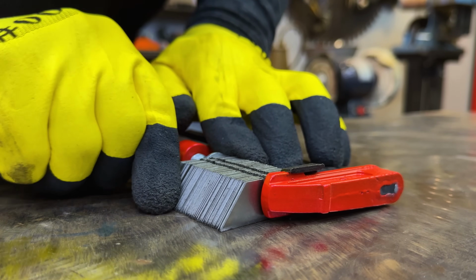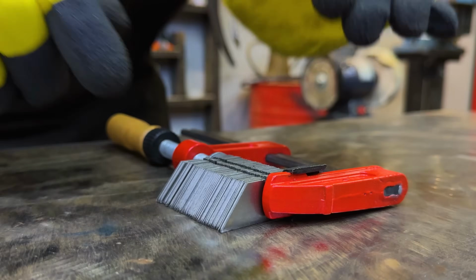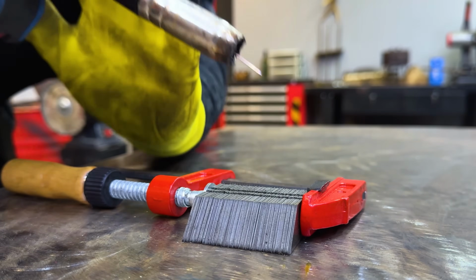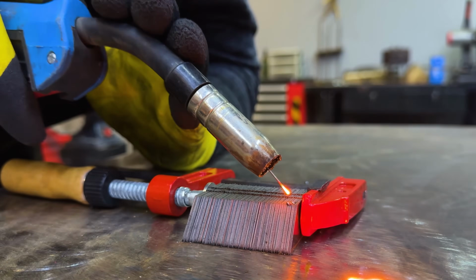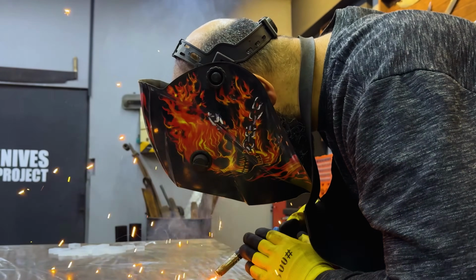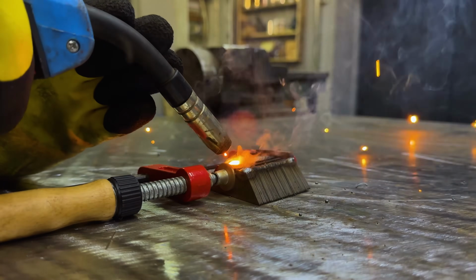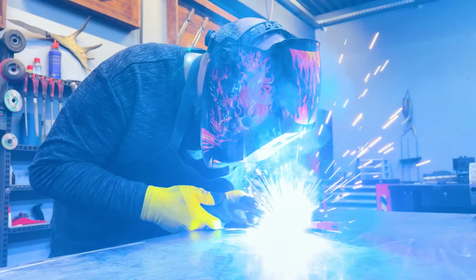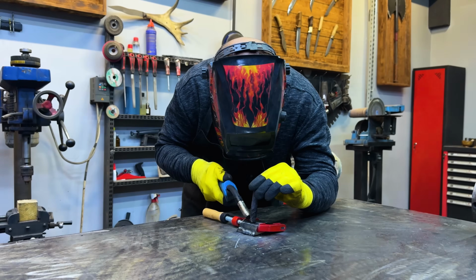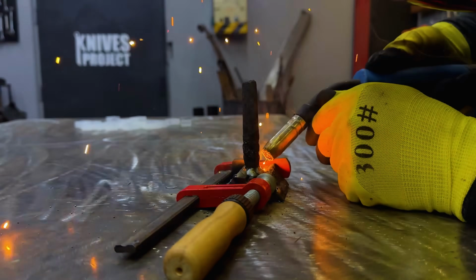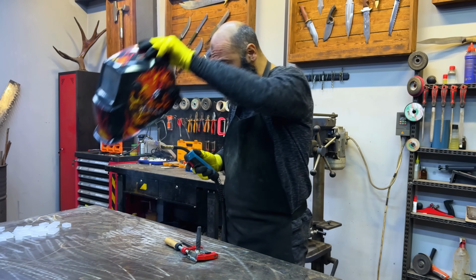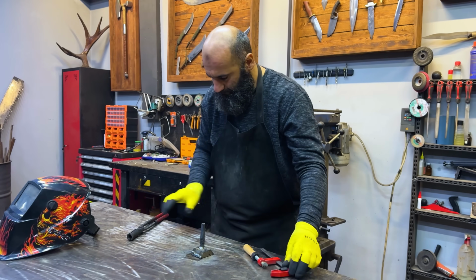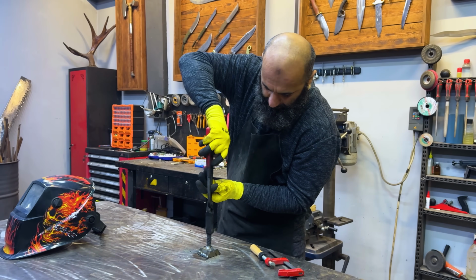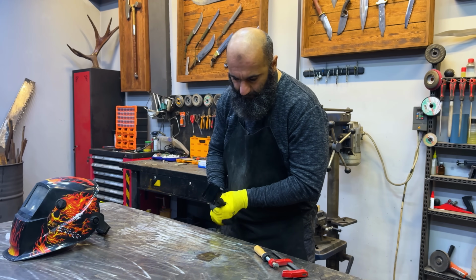Safety first. Even if my helmet looks like it belongs in a heavy metal video, we need to tack weld the entire perimeter because you absolutely cannot have oxygen getting inside, or the iron oxide will prevent the weld. This tack weld creates a mini, temporary steel can for our layers using a standard MIG welder, keeping the amps low. Get a nice, solid bead all the way around, creating a firm container for the loose blades. This is essentially the can method in Damascus forging, just without the actual can, which is a big time saver.